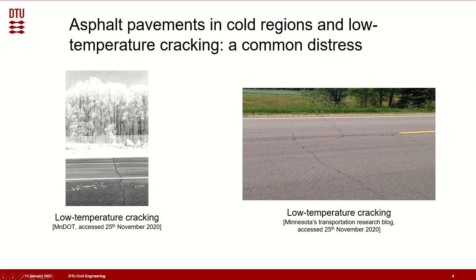Furthermore, asphalt pavements in cold regions are prone to low temperature cracking, starting from the surface of the pavement. This stress is typically manifested by transverse cracks that appear after an isolated event of fast cooling in combination with low temperature levels, or due to several cooling cycles that ultimately produce a microcrack. Due to their large lateral extent, asphalt layers are restrained from horizontally deforming. Therefore, fluctuating temperature conditions cause a buildup of thermal stresses. Specifically, low temperature cracking is induced by tensile thermal stress exceeding the layer tensile strength.